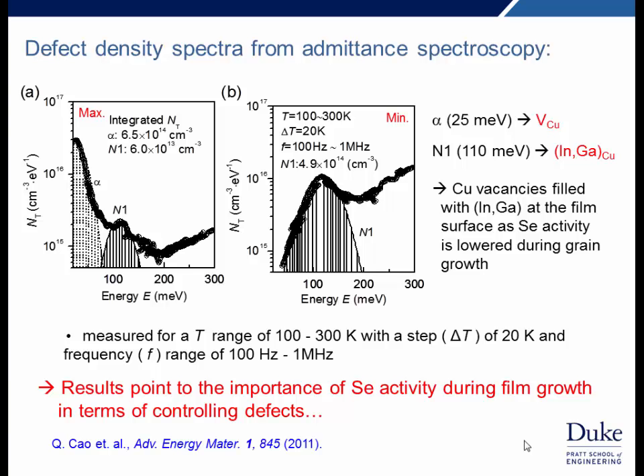And this is also evident if we look at admittance spectroscopy, which can give you a measure of the trap density as a function of energy measured relative to a band edge. In the case of maximum selenium activity, there are 2 dominant features, this so-called alpha feature, which is low energy, close to the band edge. This is what's responsible for doping in CIGS, and it's basically the copper vacancies. And then there's this deeper feature, the so-called N1 feature, which has a number of possible origins, but one of them is this indium and gallium on copper defect.